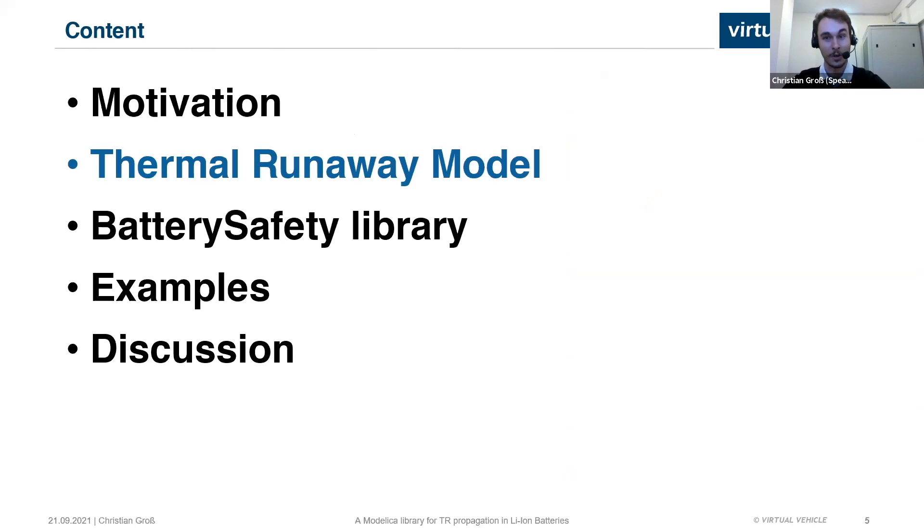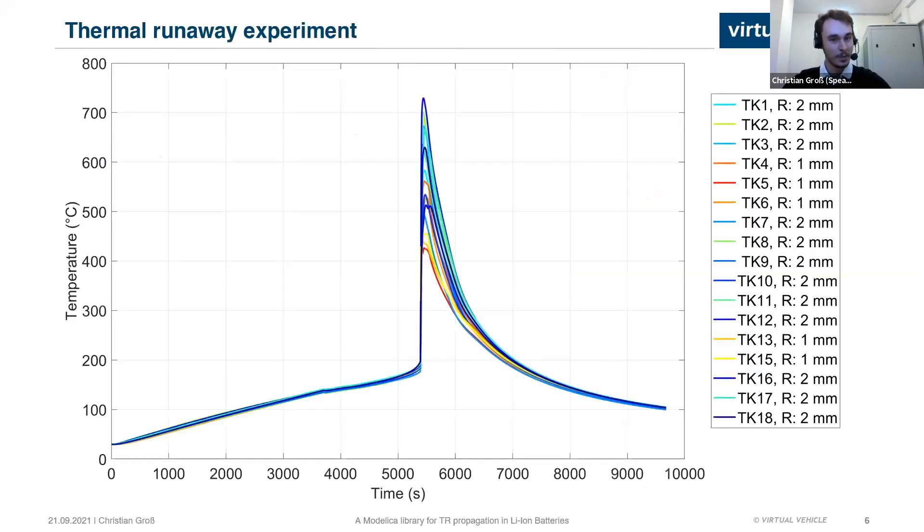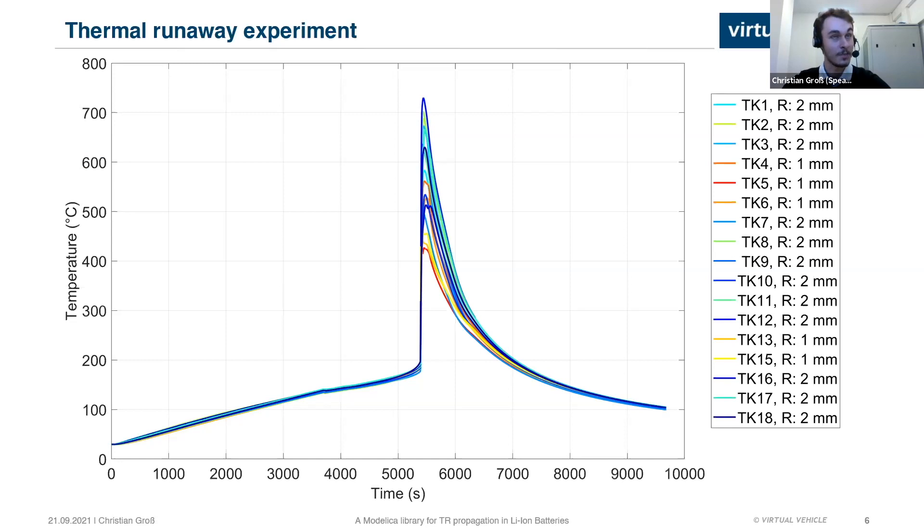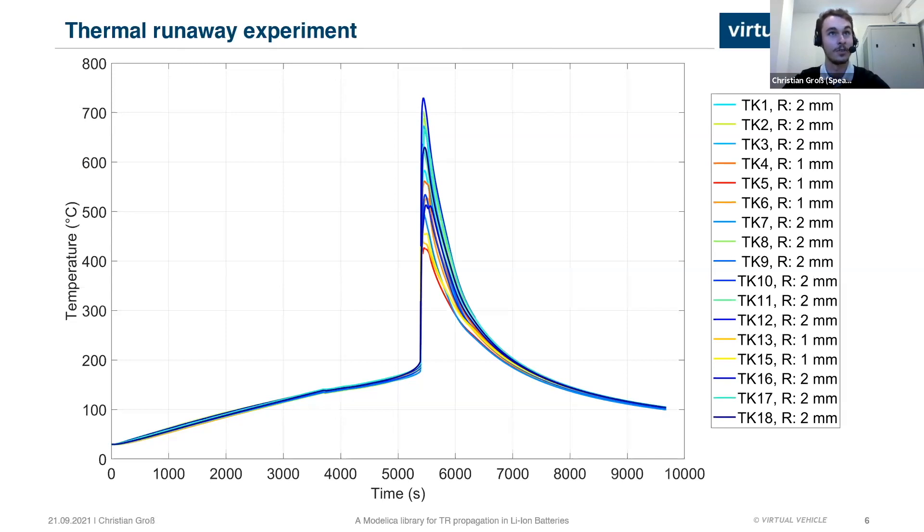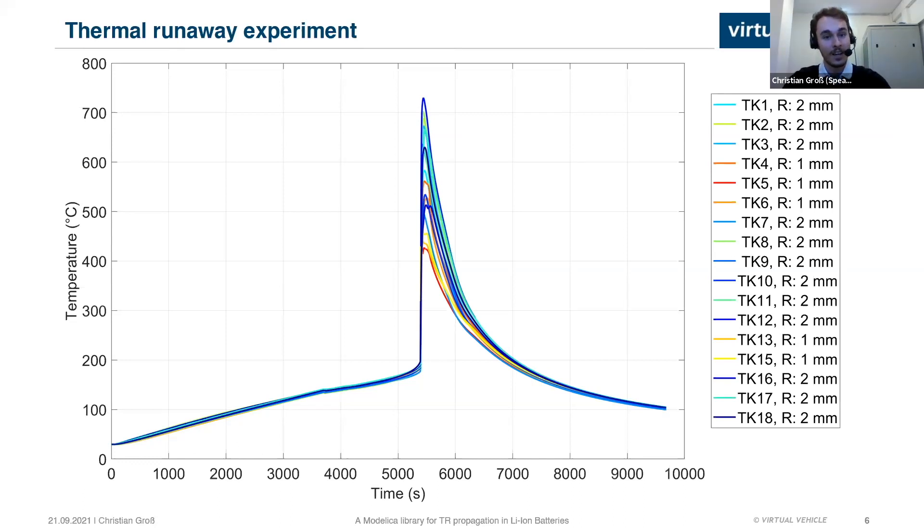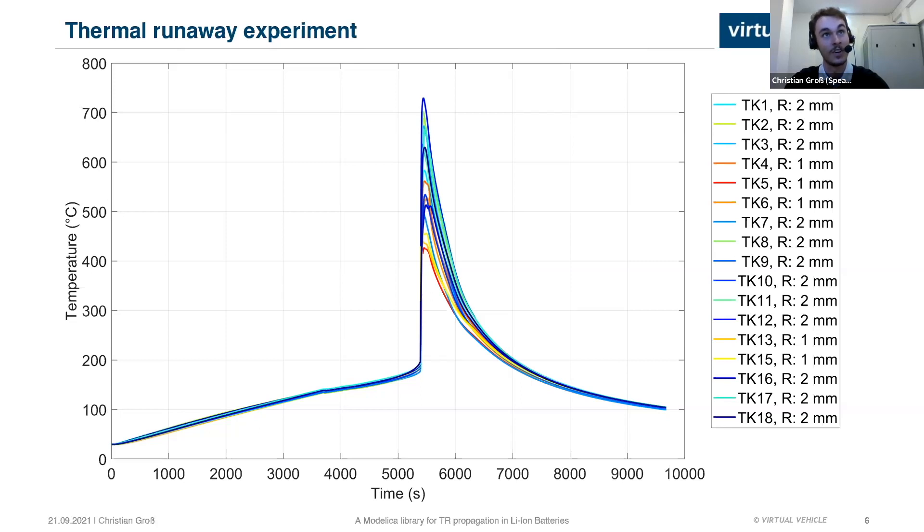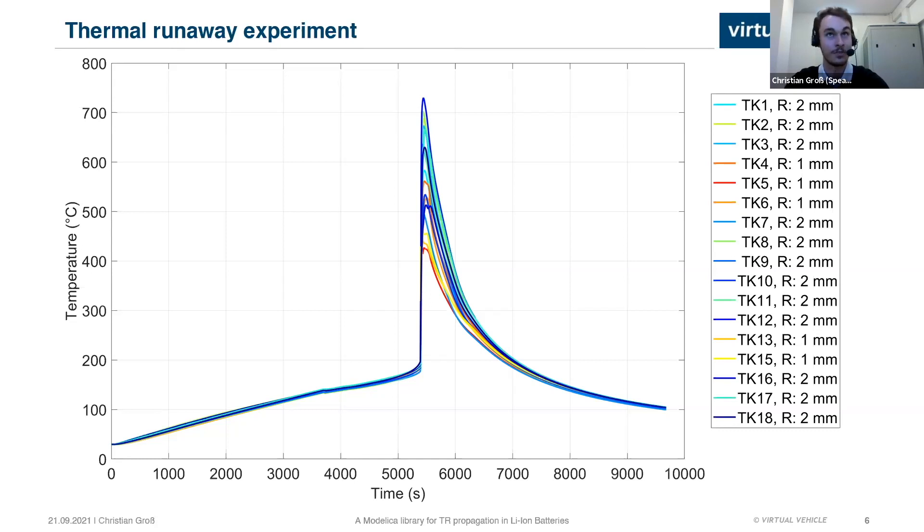Let's talk about the thermal runaway model. In this plot, you can see data gathered from a thermal runaway experiment at our laboratory. You can see here the temperature plotted over time. The temperatures are measured at the cell surface at 18 different points. You may notice a little kink at around 140 degrees Celsius. This is due to the first venting. The cell, once reaching a certain point in its thermal life, starts to disintegrate and in this process releases gas within the cell. As the cell is closed, the pressure inside the cell increases until the cell bursts open violently. We continue to heat the cell until it reaches the point at around 190 degrees. At this point, the cell transits into a thermal runaway.